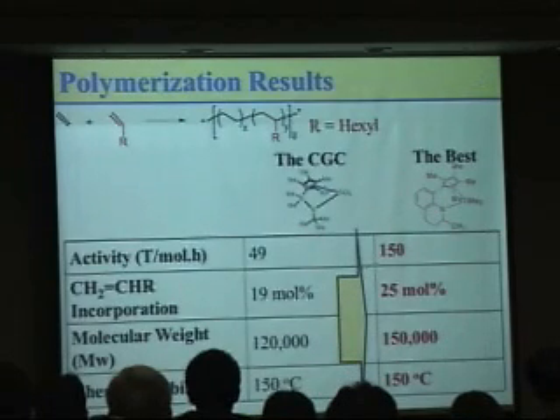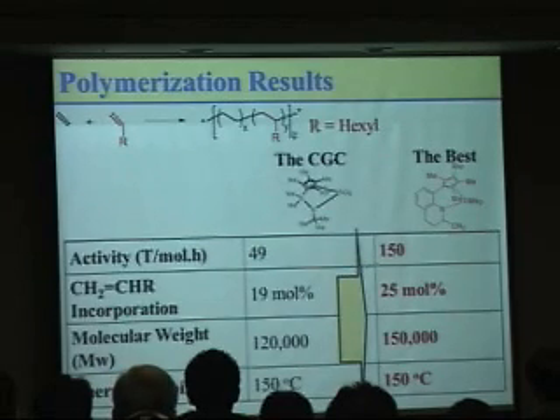The catalytic performance of my catalyst shows better activity and better α-olefin incorporation, and it provides higher molecular weight polymers. So this catalyst, in my polymerization condition, was better than the Dow CGC. And based on this research activity, LG started business in 2008, and they are doing very good business. The production capacity is still increasing, and I heard that this year LG was planning on producing 60,000 tons of polymer. The sales are around $0.1 billion.